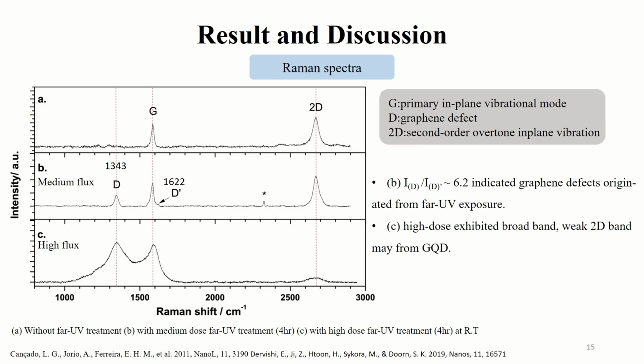In previous study, Raman spectra have been used to examine the quality of graphene. G band is in plane vibration mode, and D band is graphene defect. 2D band is second-order overtone in plane vibration. So in A part, the pristine graphene without D band shows that the pristine graphene is defectless and exists G and 2D band. And in medium flux treatment 4 hours, the D band formation confirmed that single-layer graphene has defects after far UV treatment. And the ratio of these is about 6.2. That indicates that graphene defects originate from far UV exposure.